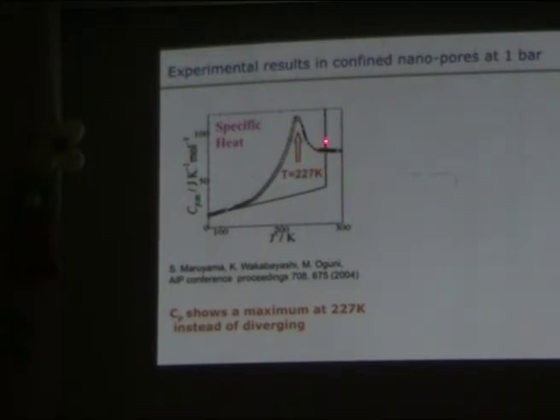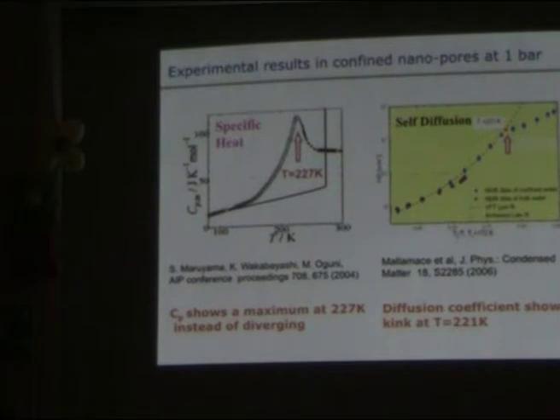This is the data that people already had back in the 1970s. You can see that the specific heat increases really sharply around 240 Kelvin, or it looks like there is a turning point at 227. But if you confine water in this nanogeometry, you find that it's not diverging, but instead there is a crossover, so there is a maximum near this point. And at more or less similar times, people also looked at the dynamic properties of the system. What they found, at more or less similar temperatures, was a dynamic crossover. The point is whether or not this is related, and whether it is linked to the critical point.